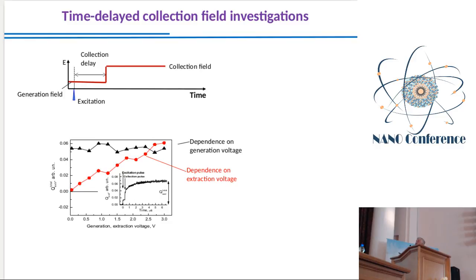In this technique, we use excitation when there is no electric field, and later we switch the electric field on. So we generate charge carriers, and if these charge carriers survive during this collection delay time, then when we switch the collection field, we can extract these charge carriers. Here we also can investigate the dependence of carrier generation on the electric field strength, and also the dependence of carrier extraction on the electric field strength.